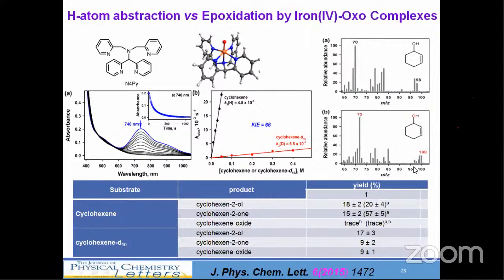So all this product analysis was done by GC-MS. Whether oxygen is labeled or not was also done. So you can see oxygen is coming from the iron(IV)-oxo species. So 70 becomes 72. All those things were done, and you can see the products were quite high in the case of cyclohexene, but some epoxide was also obtained when we did a catalytic reaction.